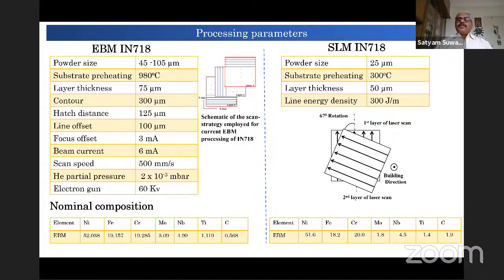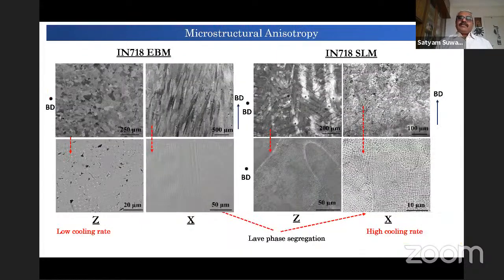We almost optimized the parameters in both cases to the best possible density available, and with those variations of parameters we could make these materials, and these are the results shown, the best output of these materials. We could see there is a subtle difference between EBM and SLM. Microstructures are characteristic of the cooling rates encountered during the processes, but in both cases the cell structure is more pronounced in selective laser melting, and the microstructure is more lamellar type. Melt pool boundaries are more pertinent in the selective laser melting process than in the EBM process.